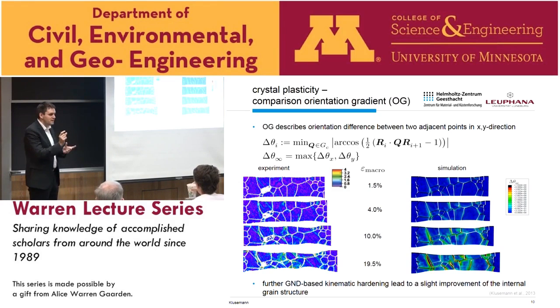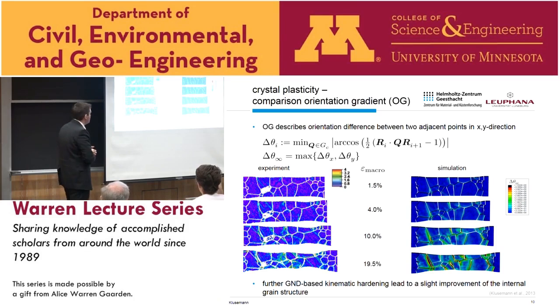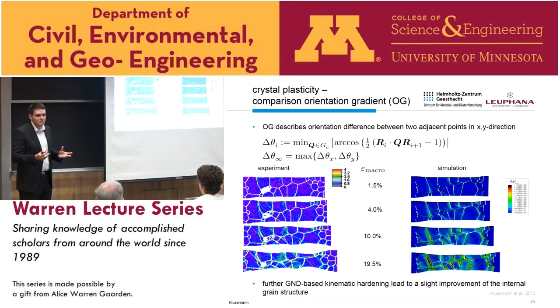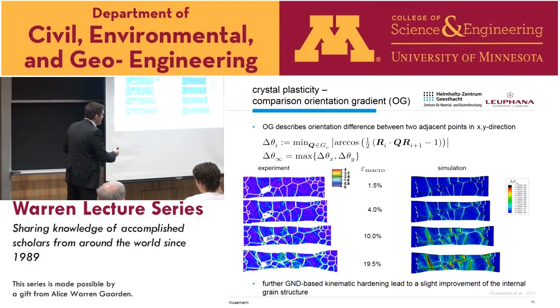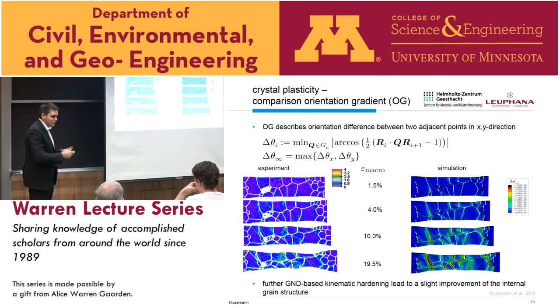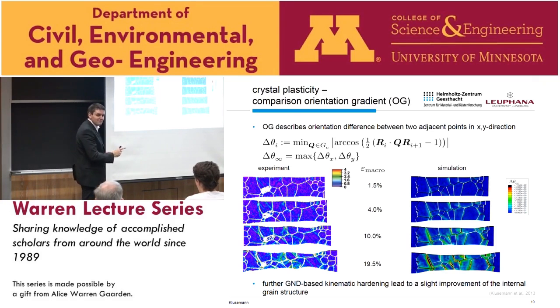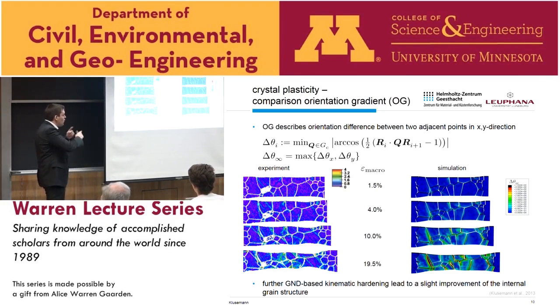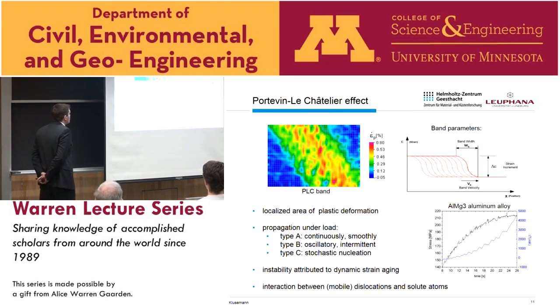However, I have to say the grains are already so large, approximately 2 millimeters grain size diameter, that the effect was not very large. We had an improvement of 3%, which we measured. So this is not really much help, but we could see it. There was some improvement.